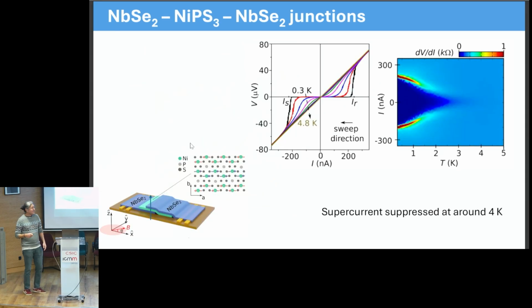So going to the measurements, when we measure these at low temperatures, we see supercurrent, so we see a Josephson effect. Great. We see that the supercurrent is not very high, and that's the reason why it's suppressed at temperatures lower than the critical temperature of the leads. But that's fine. We're already happy we measure a supercurrent. Now, we apply a magnetic field to do the test that I mentioned before. So, is this supercurrent distribution homogeneous? And also from these oscillations, one can infer the geometrical dimensions of the junction.